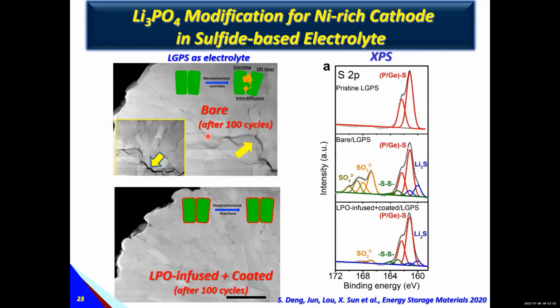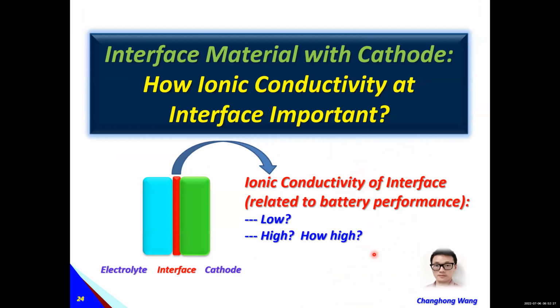For example, we have a cross section. We found without coating and annealing, we have big cracks on 811. With the coating and annealing, with the coating again, you can see it is better. But still, you have some reactions. Without coating, they have reactions from XPS. With the coating and annealing, with the coating again, it can significantly prevent the reactions.